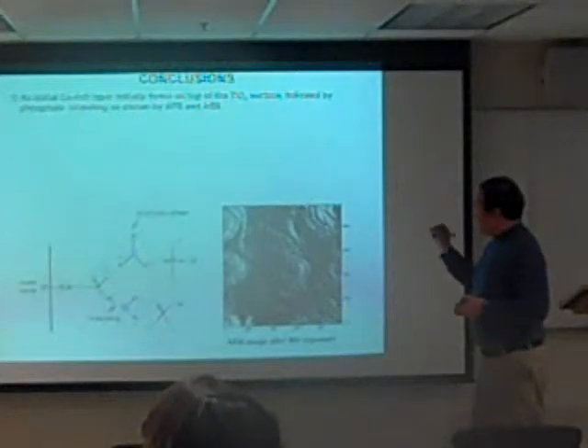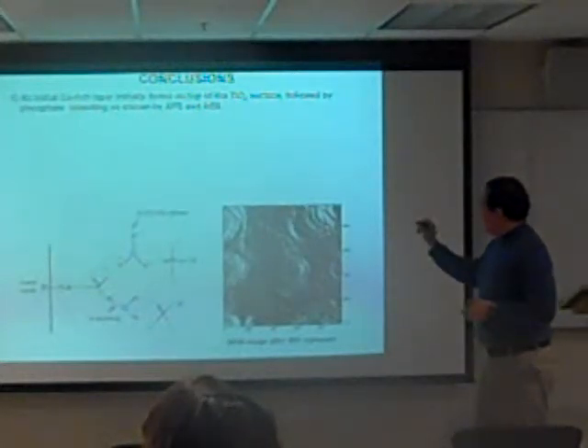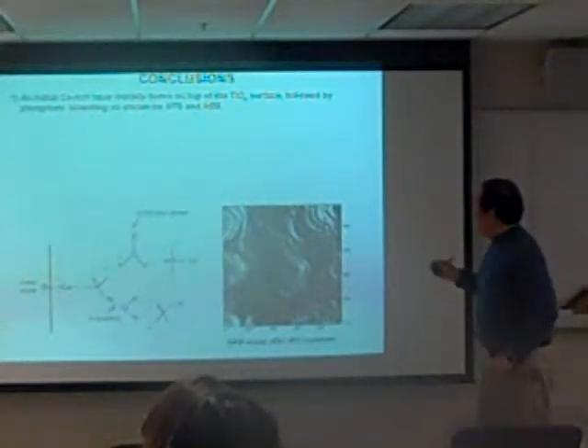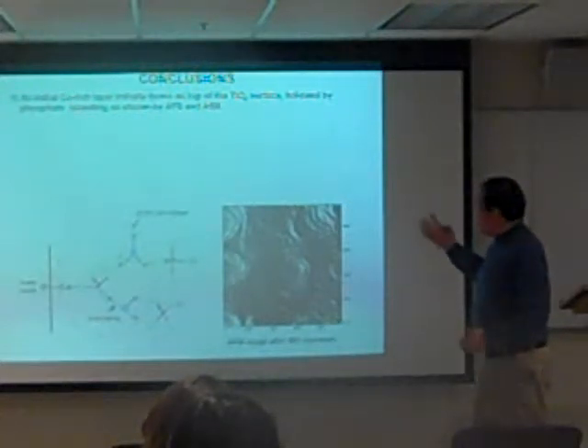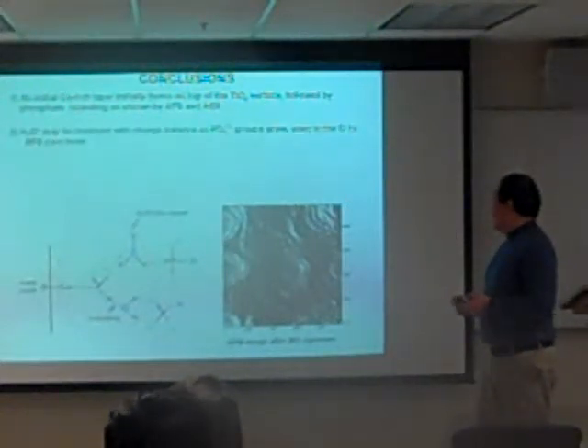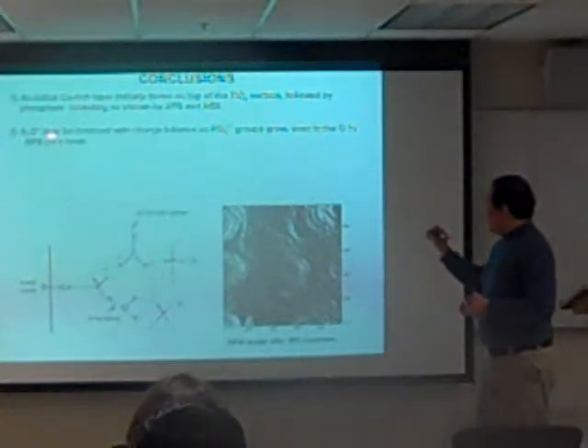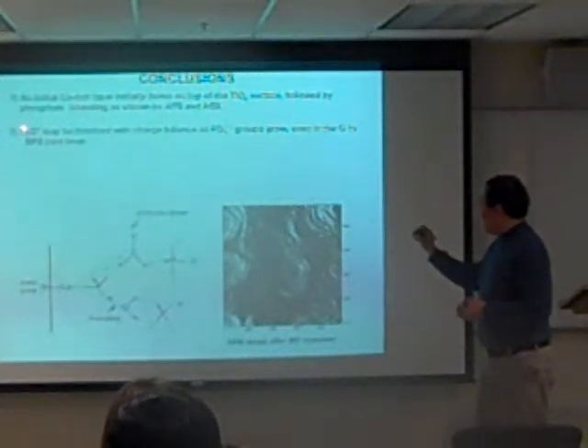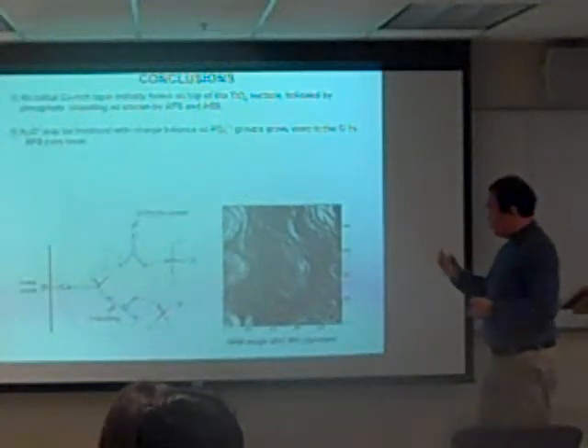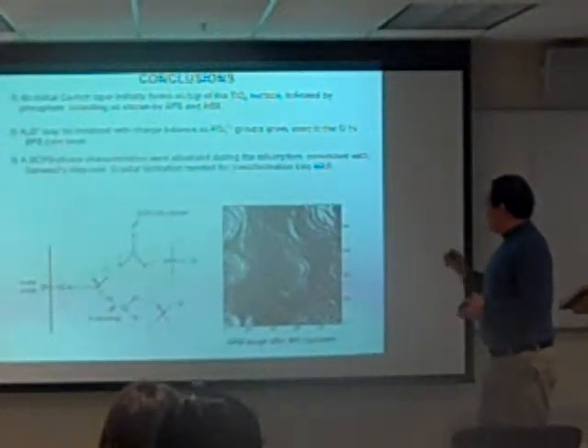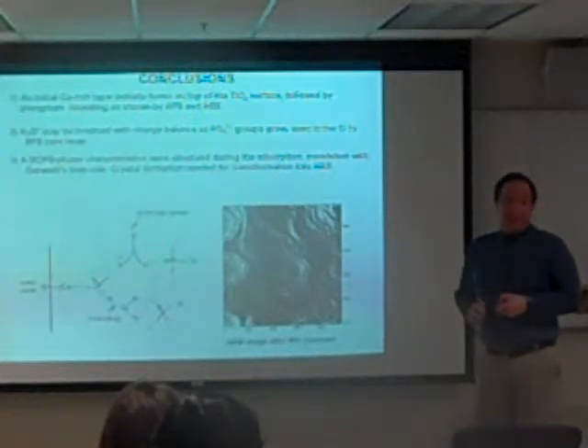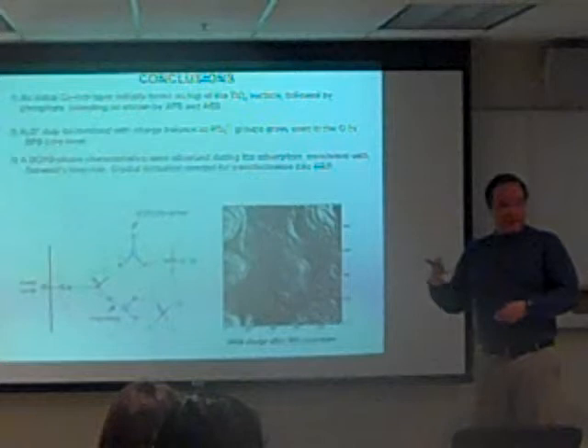That's what we have. So, in conclusion, for this first part, we see that as calcium phosphate grows onto the TiO2 metal oxide surface, it starts with an initial calcium-rich layer, followed by phosphate islands, and then we just postulate that this is the source of the charge balance, and so we see brushite-like characteristics, and that's the least thermodynamically stable phase of the calcium phosphate.